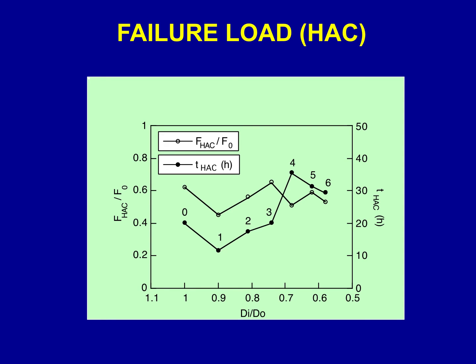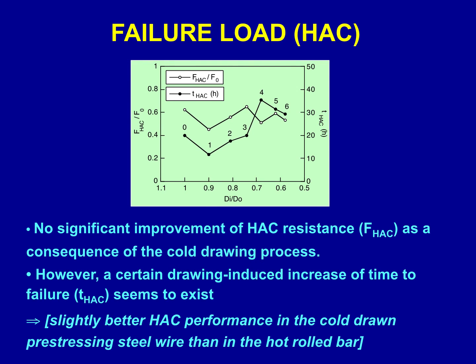What do we see in this plot? With regard to the evolution of fracture load, we cannot observe any specific trend, but with regard to time to failure, there is an increasing trend. Here we discuss this plot. No significant improvement of hydrogen-assisted cracking resistance, represented by the load F HAC, load in hydrogen-assisted cracking situation, as a consequence of the cold drawing process. The fracture load under hydrogen-assisted cracking conditions does not strongly depend on the degree of cold drawing, the ratio of diameters.